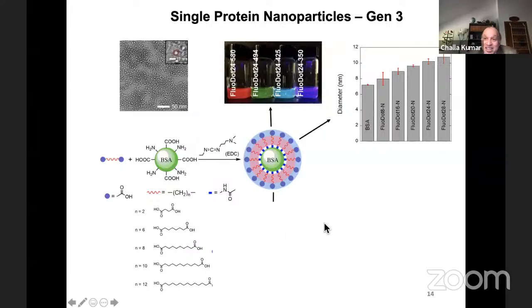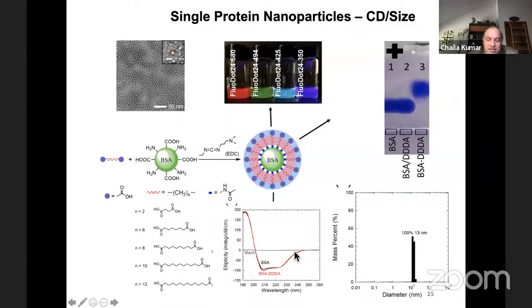It's very hard, and here it is done systematically, not by hit and trial. And those who are biochemists may recognize that this protein is chiral, and so it has a circular dichroism. Before versus after synthesis, you have essentially the same circular dichroism band, meaning that the protein, even though we have taken a hammer and hit it dramatically, still retains its structure. This is the beauty of proteins. And this is the gel electrophoresis evidence that we actually changed the size and charge of the protein, et cetera.